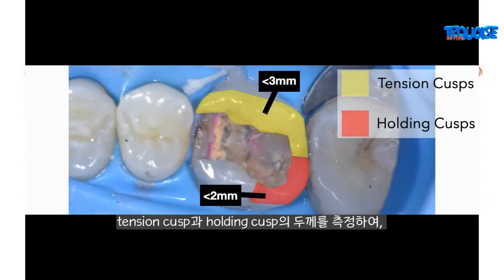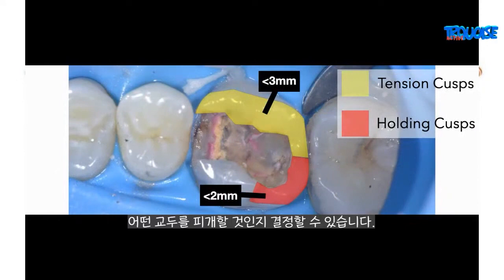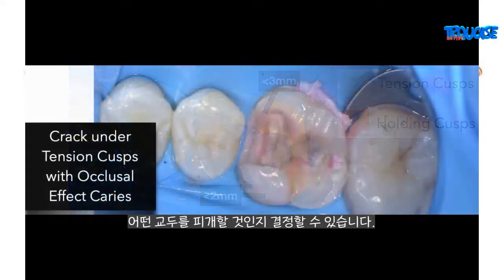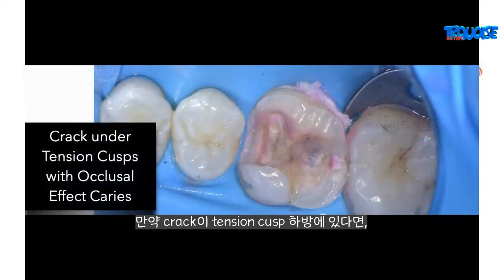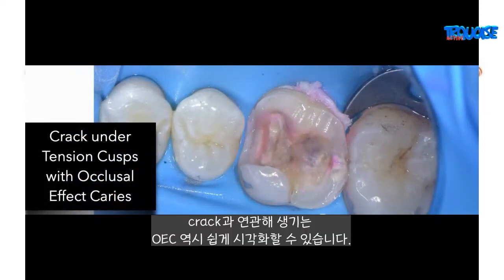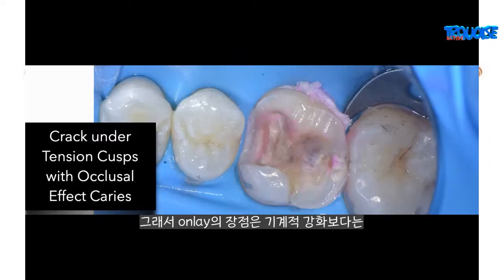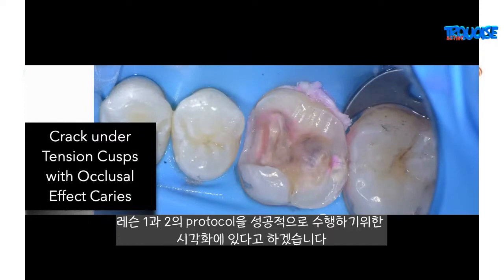So the measurement of the tension cusps and the holding cusps allows us to make decisions on which cusp to onlay. And if a crack is under a tension cusp, it's easy to see that by onlaying it. And so the occlusal effect caries that can happen associated with the crack is easier to visualize in these cusps that are onlayed. So the advantage of onlaying a cusp is more of a visualization to ensure lesson 1 and lesson 2 accomplishment of those protocols rather than a